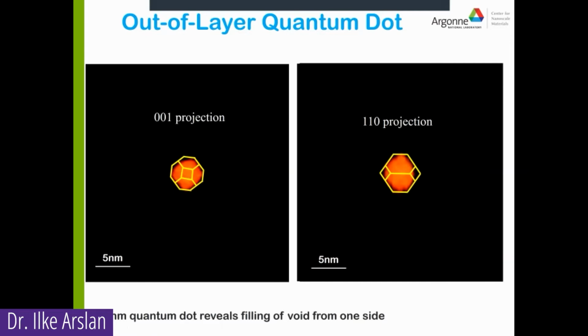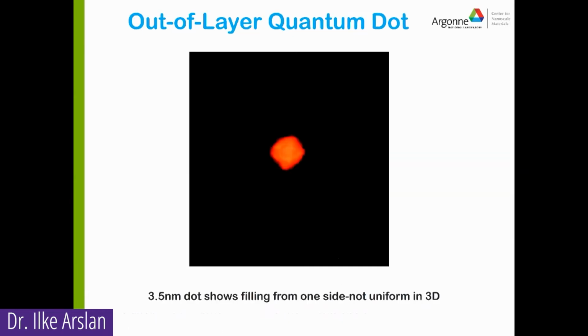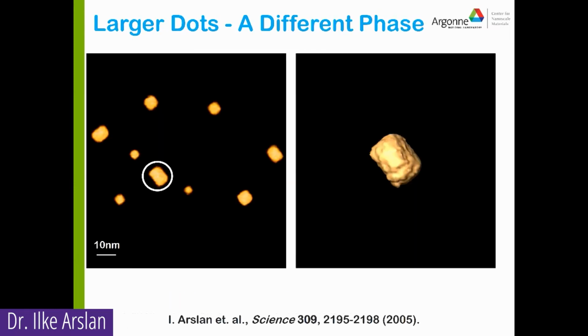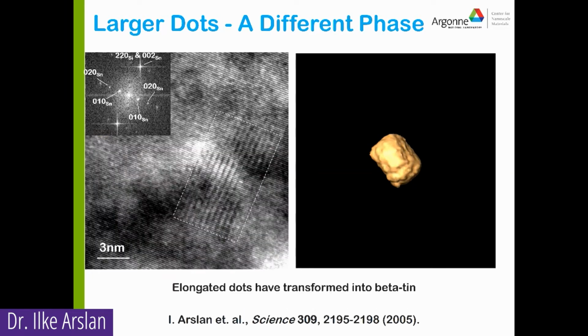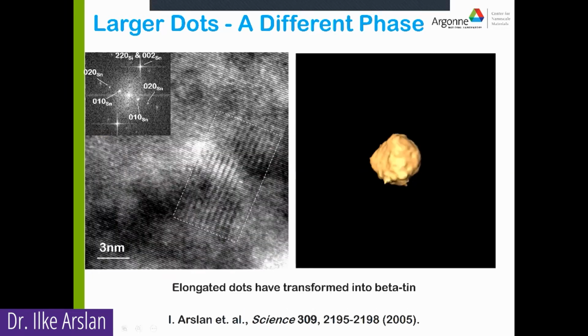There's a longer story to this, but basically what was happening is that there are voids in silicon that are exactly the same shape as these quantum dots form. So the tin was diffusing out of those layers and into those voids, and it was filling by Stranski-Krastanov, which means it was doing one monolayer coating and then growing 3-dimensionally from one side to the other. So that was the new science that we were able to do based on technique development. And here is that beta tin quantum dot, which was in a different shape than the others.